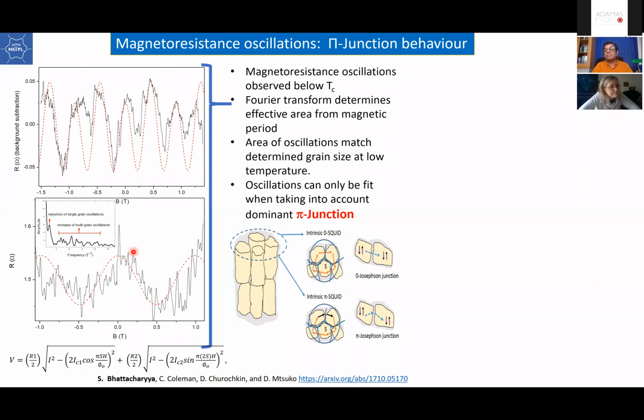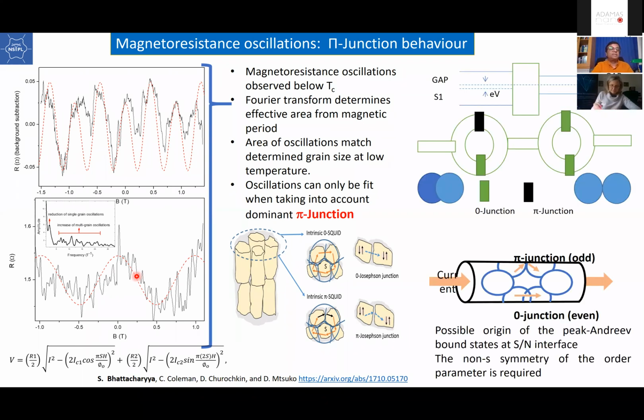And you can do Fourier transformation, and you can calculate the size of the grains from these oscillations. So from this extensive data set, we can make a model of the material based on the microstructure, that you have grains and you have zero junction and pi junction. And this is very important. This is the signature of the nanodiamond, and this will be very important for making a new kind of device.